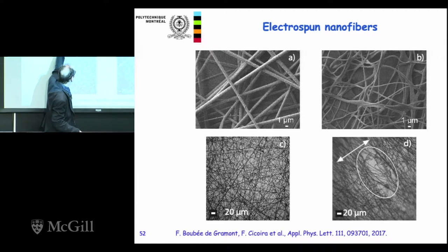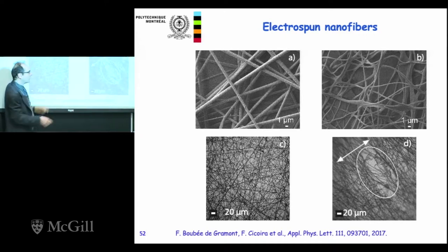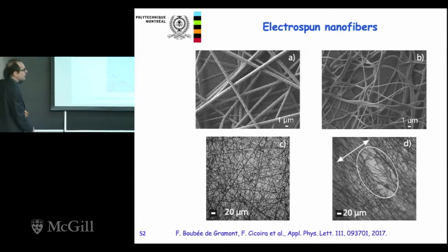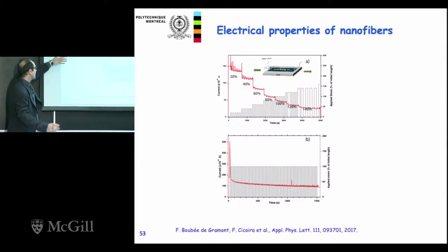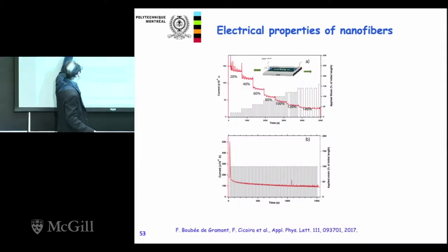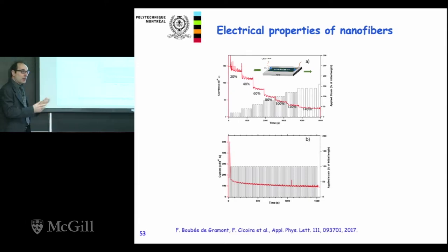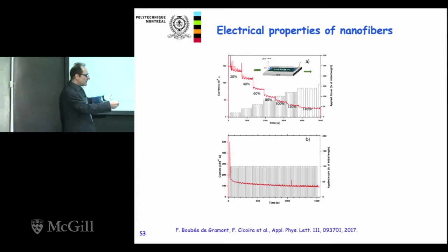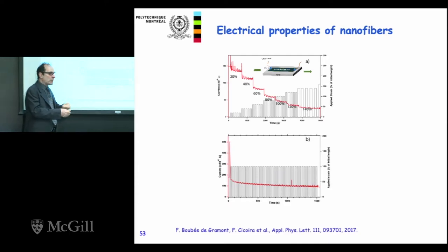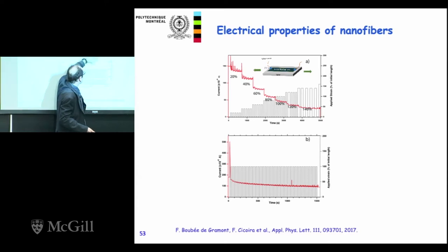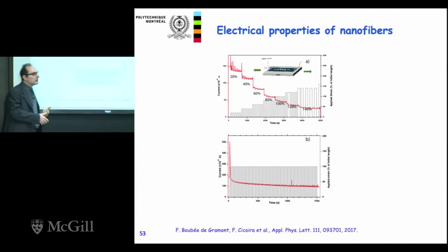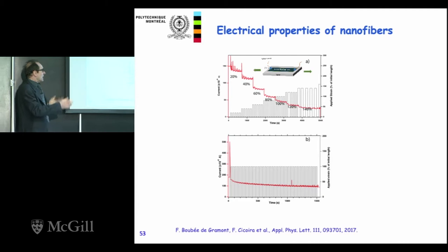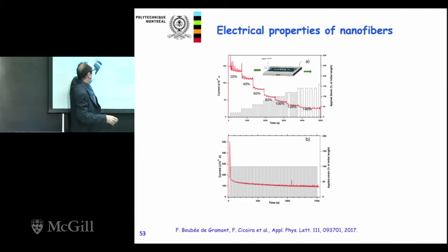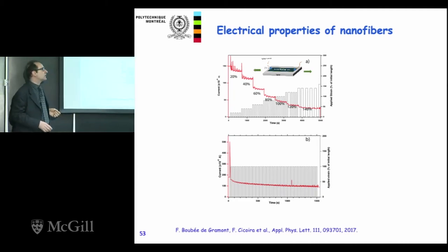So these are the fibers after the electrospinning and polymerization. These are after the dissolution of the core. And actually, you can make interesting things with these fibers. These are like an attempt to get stretchable conductors. As you can see, of course, the fibers are random, so the conductivity is also random. So if you stretch the material along a certain direction, you will break some of the fibers, but some will survive. And you can actually stretch your material up to more than 100% of initial length while still keeping a certain conductivity. It's not ideal because the fibers are not oriented, but it's also another interesting way to get stretchable electronics.